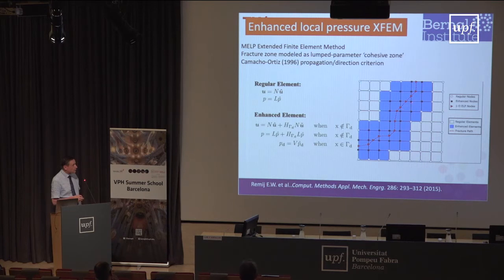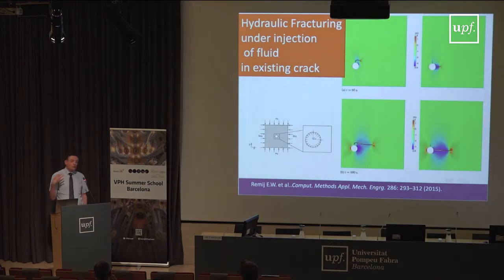And this is very standard stuff. Only what we did along the crack is that we had pressure defined inside the crack, but also a pressure defined on the left side of the crack and on the right side of the crack. We had three pressures at each point, because we expect these three pressures to be systematically different inside gels. And so we allow fluid to flow from the crack into the formation, into the gel, and within the gel it is flowing as well because it's porous media, and also within the crack it is flowing. So these three things are accounted for.